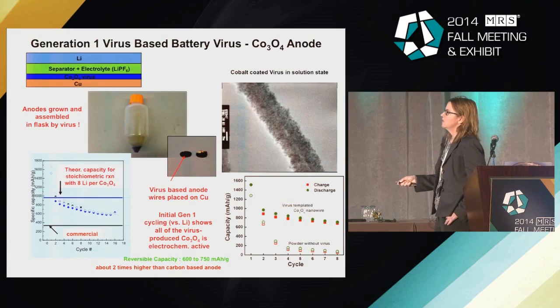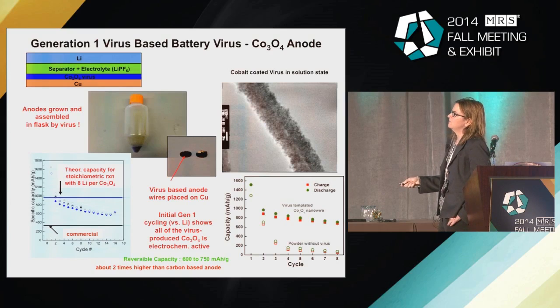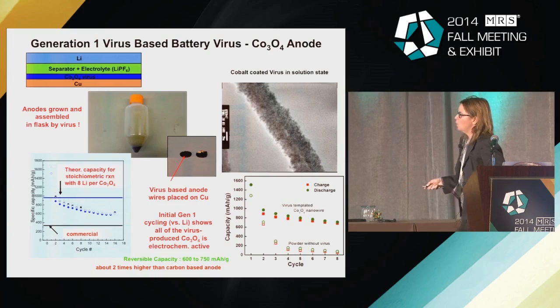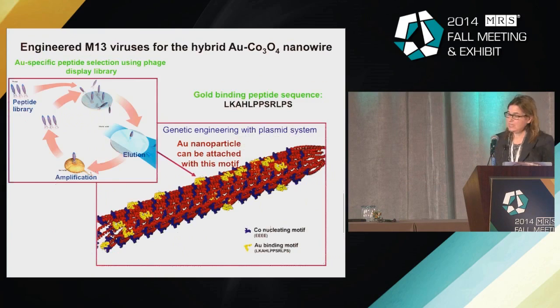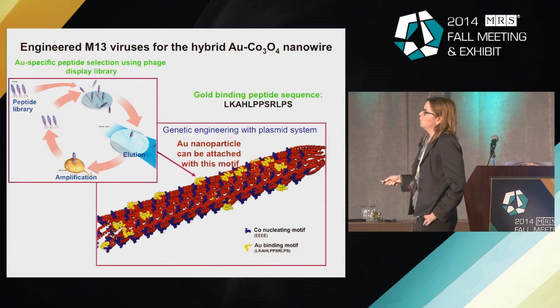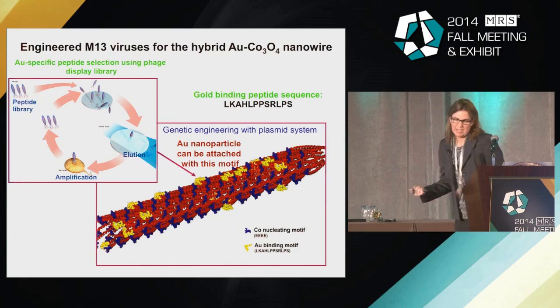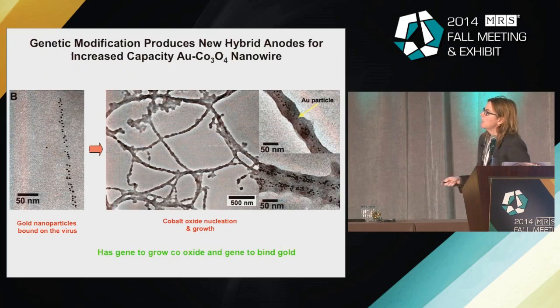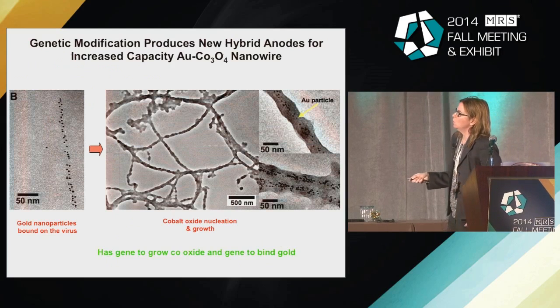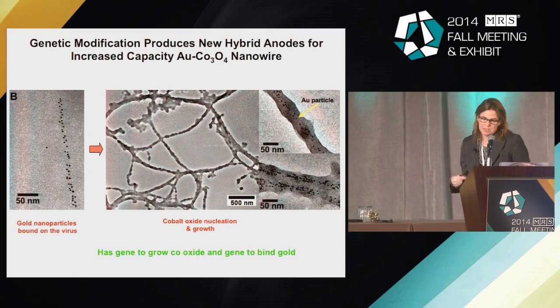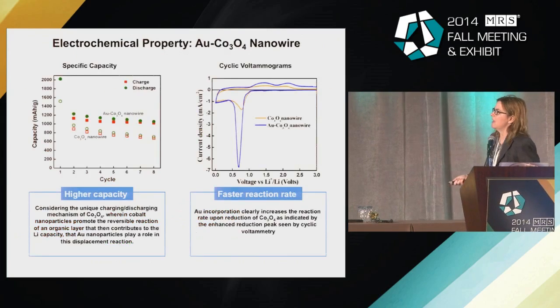I always say this is the first data my students showed me. You can see that it hits theoretical capacity at first, and then as you cycle, it starts to fade. So what my student, Kite, decided to do was go in and give this virus a second gene, one to grow gold and another one to be able to simultaneously grow cobalt oxide. So this is a virus that's binding gold. Now you give it cobalt oxide and it zips up the structure. And now you have a cobalt oxide gold complex, and you can test that as a battery electrode.